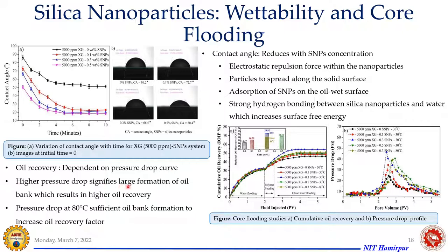So that's why you can see here oil recovery itself depends on the pressure drop curve. A high pressure drop curve signifies large formation of oil bank, which results in high recovery. So that's why you can see a high pressure drop curve at 0.3 and high recovery at 0.3. And the pressure drop curve at 80 degrees centigrade shows sufficient oil bank formation to increase the oil recovery. Even when you're at 80 degrees centigrade, the pressure drop is this line you can see here, and because of this you can get a promising result when you're implementing nanoparticle nanofluid for this.